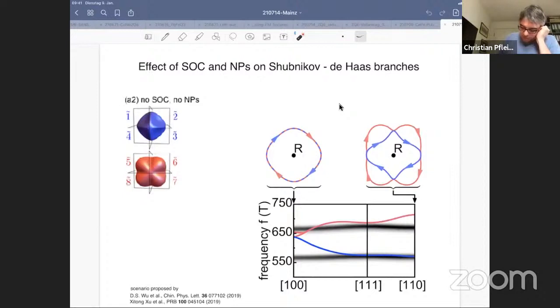if you orient the field along the 100 direction, right, it turns out actually they are roughly the same size. It turns out that actually they intersect. Right. So, but here they are essentially the same size. So you have dominantly 1 frequency, right? And not the 2. The black is basically our experimental data, and the red and the blue curves here are the theoretical calculation with spin.